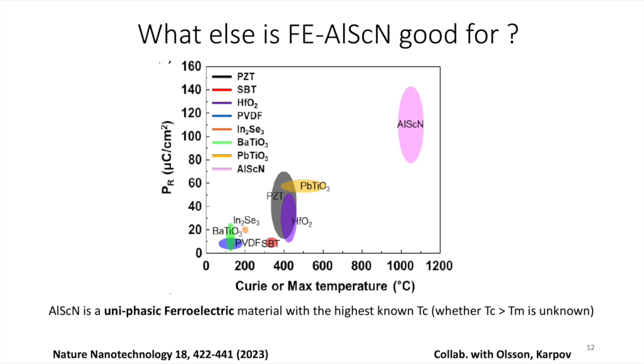Similarly, there are Curie temperatures for electric polarization, which is the Curie temperature for ferroelectrics. So that's what I'm saying over here: once you program information into this material, at temperatures up to 1100 degrees C that we and others have measured, it does not lose its polarization. Because the Curie temperature, we don't know. It may be even higher than 1100 degrees Celsius. We don't know for sure. Maybe the material gets destroyed or obliterated before it stops being a ferroelectric, right? I think you have to actually thermally destroy the material before it loses information. It's that stable. Right? So this 1100 degrees Celsius work was done by Germans.